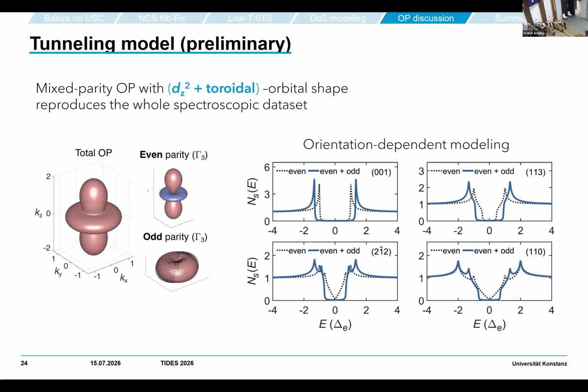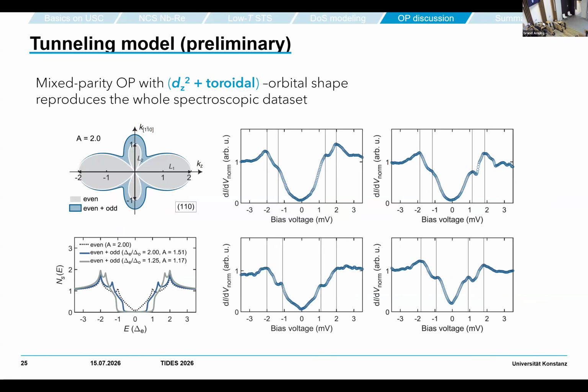So this is the theory part, and then we can compare this with our experimental findings. I only show one example for the 110 direction, where we saw these double structures. The pattern is that we have a cut through the order parameter with two large lobes, with an extension of 2 in these units and 1 in the perpendicular direction—basically the superposition of these two extremal lobes, which can explain the two peak positions.